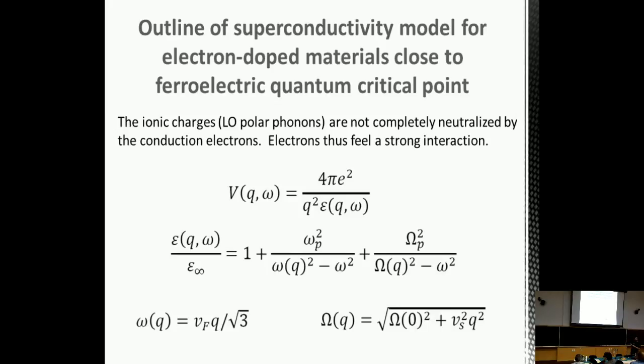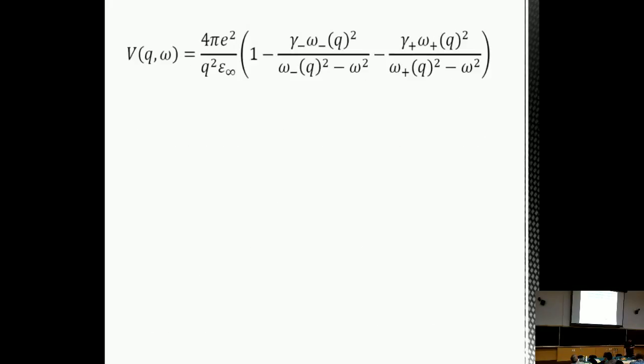So we can rewrite the dielectric function, and in fact the interaction. If we put the dielectric function into the interaction and rewrite it in this form, we can identify new modes, normal modes of this coupled electron-phonon system.